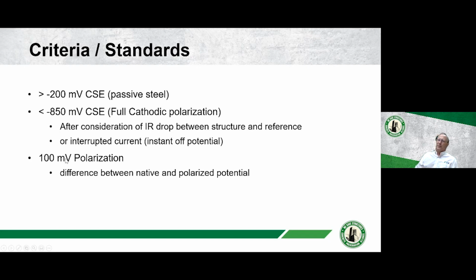And the most important, most commonly used criterion is the 100 millivolt polarization criterion. That's between the native, or non-energized, potential of the reinforcing steel and the polarized potential. So if you start out with 300 millivolts as a native potential and you polarize it to 400 millivolts, you have achieved the criteria for cathodic protection.